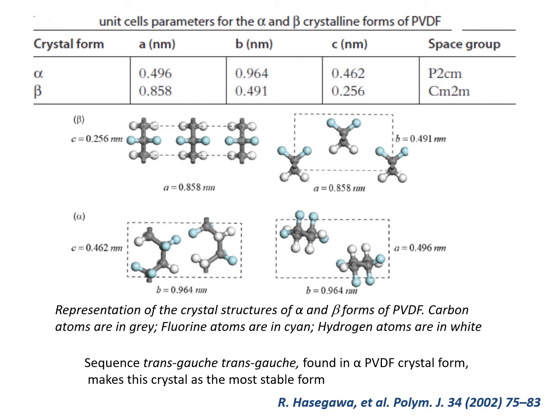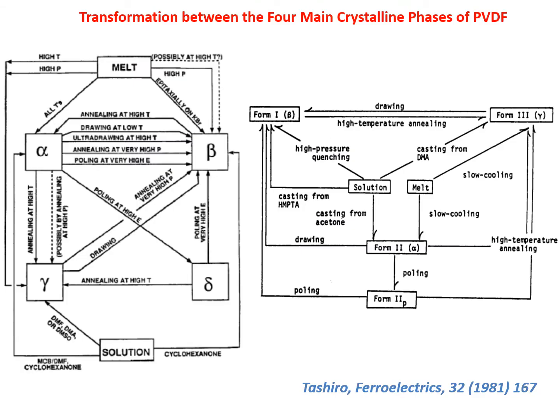And as you can see, Hasegawa 20 years ago reported the alpha and beta crystal forms and led to the a, b, and c parameters of a unit cell. So you have an organization, of course, in the system. The alpha and epsilon are non-polar phases, while the beta, or trans, leads to a zigzag phase. So probably you are familiar with this system, because if you want to get some beta polymorphism of PVDF, you have to investigate a lot of chemical or thermal processes.